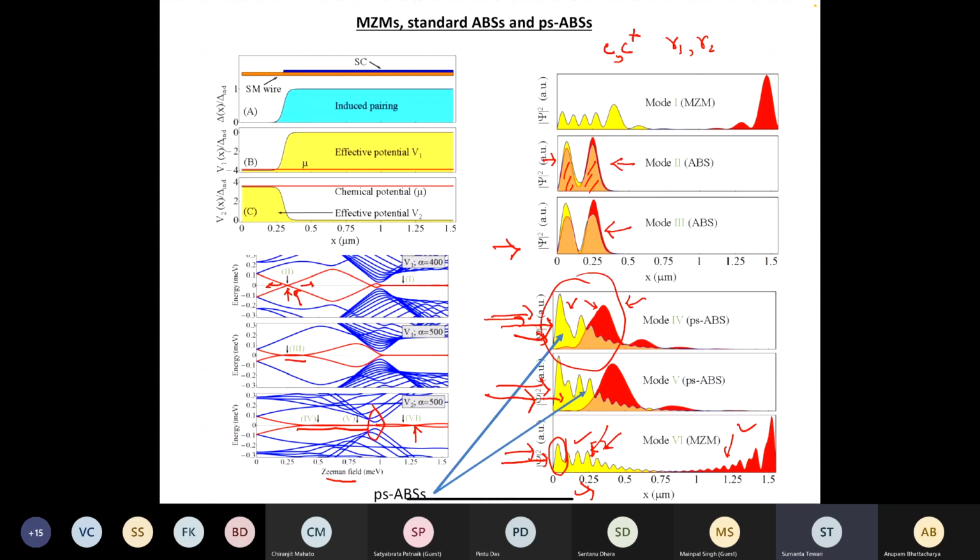Now, the issue is, when you do the proximity-driven superconductivity, all these heterostructures, it is generally found that it is S-wave. You don't find examples of P-wave. You may claim it to be Majorana there or not, but there is no evidence that in the heterostructures, P-wave superconductivity has been seen. So there is a fundamental question whether these are true representatives of topological superconductivity. Whereas in copper-intercalated, niobium-doped and strontium-intercalated bismuth selenide, P-wave px plus ipy has been seen.